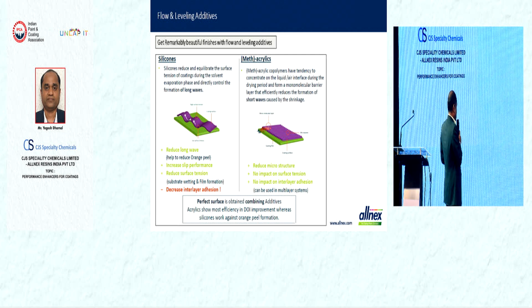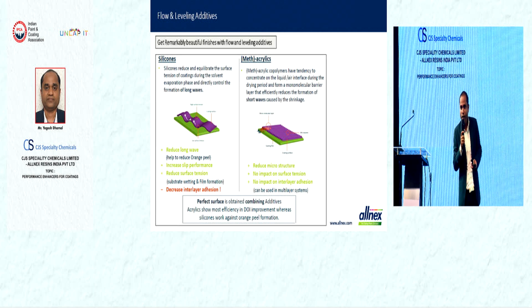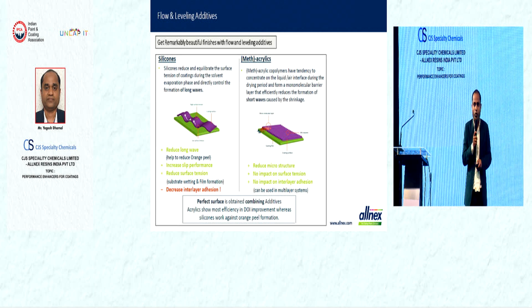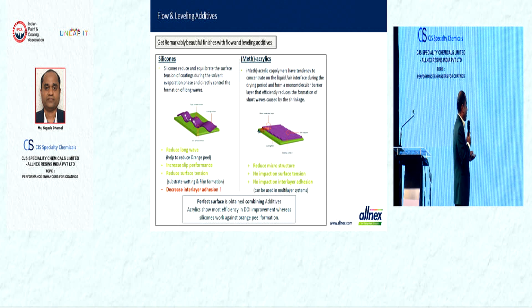Silicones reduce the surface tension, that's why they help to improve the slip performance. Acrylics don't have an impact on the surface tension, that's why they don't have any impact on the intercoat adhesion. And the summary of this slide is we generally recommend a combination of both technologies, both chemistries, silicones as well as acrylics. So what perfect surface is obtained by combining additives? Acrylics show most efficiency in DOI improvement, whereas silicones work against orange peel formation.